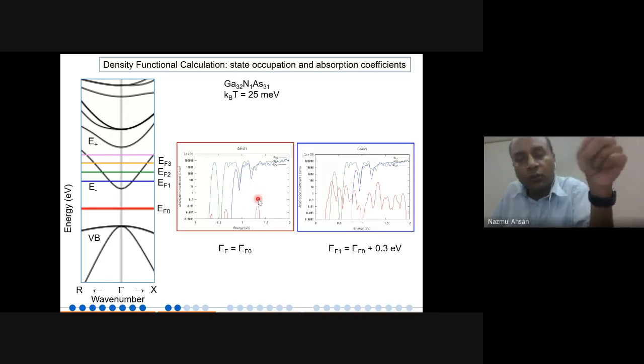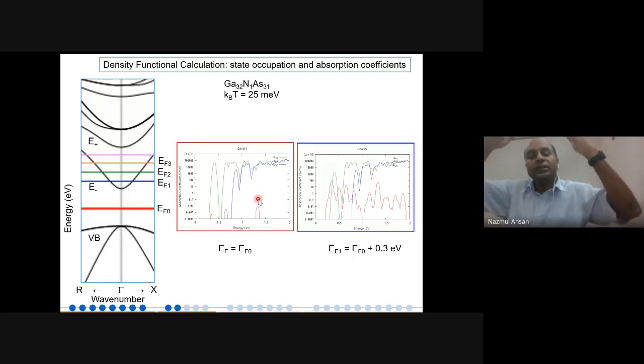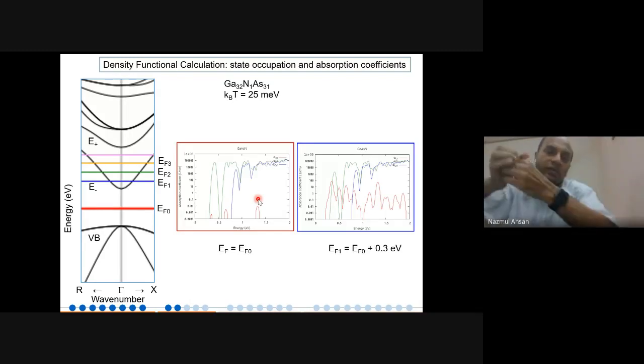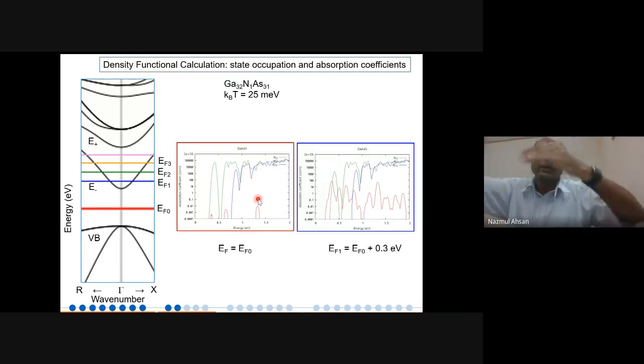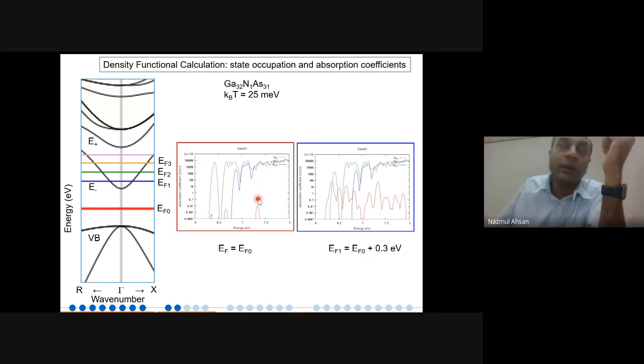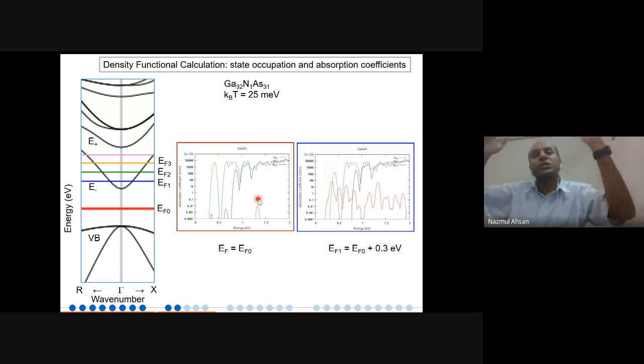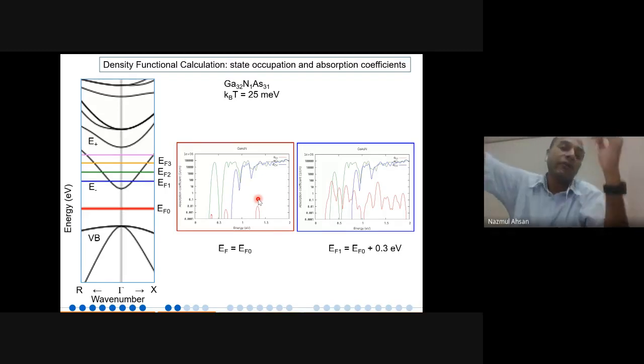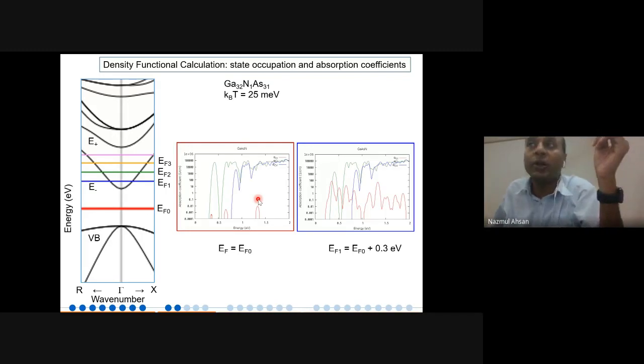And I told you in one of the slides that you have to match the absorption coefficient. If one absorption coefficient is very wide and another is very thin, there is a mismatch, then you cannot bring out the maximum potential. The maximum potential is that through your intermediate band, the number of electrons excited to the intermediate band should be excited again by another photon to the conduction band, and if they absorb in a similar amount, then you have the highest conversion efficiency.